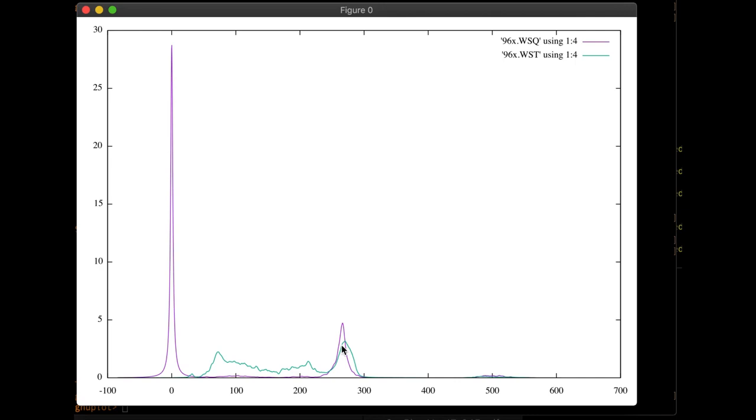Now in this plot I see that after the projection I have the violet line which in fact consists of two peaks. The peak at zero is just the acoustic mode which is not of much interest. And then we have the mode which corresponds to transversal optical at the zone center. This is the peak which is relevant for comparison with the Raman spectroscopy or infrared spectroscopy because in these techniques the vibrations are probed which are at the zone center. Whereas in the total density of states we have the spreading of different modes over a large range of frequencies. So after making this projection onto the q equals zero the comparison with the spectroscopy results are more easy, more straightforward. And then concentrating on the details of this peak one can draw certain conclusions about the nature of vibrations at the zone center. Thank you.